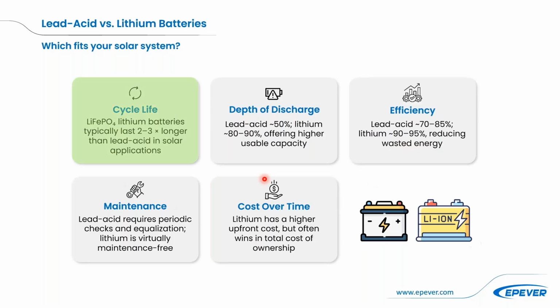Cycle life. Lead acid might give 3 to 5 years, but lithium often gives basically 2 to 3 times higher life cycle in comparison to lead acid batteries. So depth of discharge is also important. Lead acid 50%, lithium 80 to 90%. Efficiency around 70 to 85% for lead acid, and then we have 90 to 95% for lithium batteries. No maintenance for lithium, or low maintenance, shall we say. And the higher upfront cost for lithium, but often cheaper in the long run.